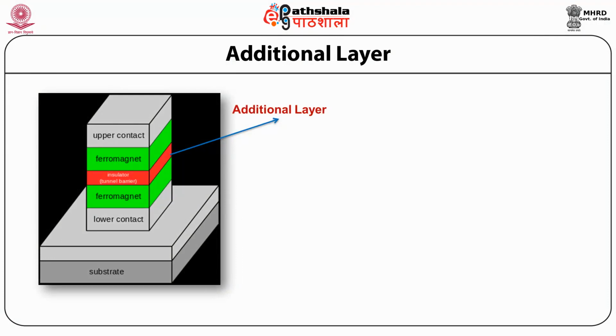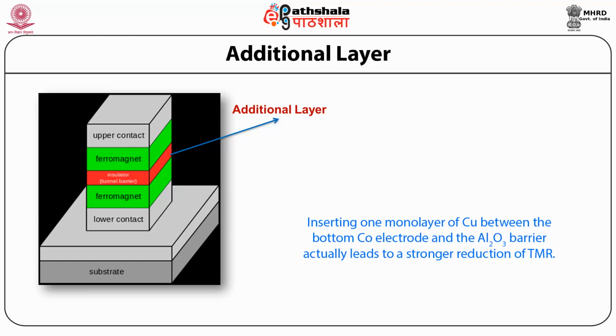Inserting an additional layer at the barrier ferromagnet interface has been investigated to rigorously probe the origin of tunneling spin polarization. It was shown that inserting one monolayer of copper between the bottom cobalt electrode and the Al2O3 barrier leads to a strong reduction of TMR. Yuasa et al. in 2002 have further developed these experiments by achieving sharp interfaces between single crystalline Co(001) and Cu(001) using molecular beam epitaxy.